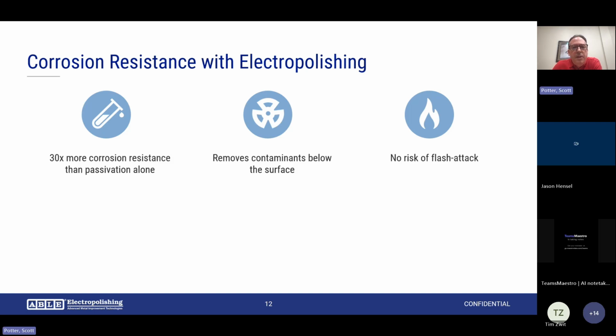I guess I had a question about what is flash attack. Flash attack is when the grain boundaries of the material are actually attacked chemically. So you get an adverse reaction between the chemicals and the actual material. So it can actually be detrimental and can cause premature fatigue life failure. And so, yeah, flash attack is definitely something you want to avoid.